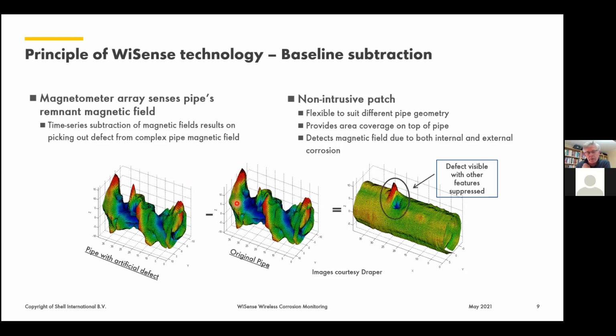By subtracting these two fields, you get a fairly smooth background. And suddenly the defect contribution is very clearly visible. And this can be done because the sensors are attached permanently to the pipe and in such a way that they are not moving around. And that allows you to subtract the original baseline from a later measurement where a defect could develop. And this is the principle that makes our monitoring tool work.